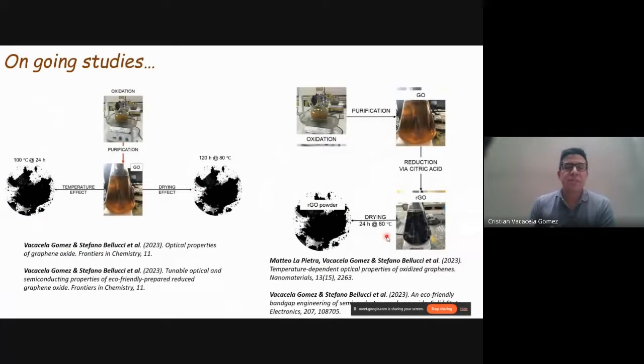Another important thing that we need to keep in mind is, if we are going to synthesize these materials, we also need to control several parameters during the process. For example, once we get the graphene oxide dispersion, like here, we can play with the temperature effect, for example, increasing the temperature from 40 centigrade to more than 100 centigrade to remove the water and just take graphene oxide. Or we can also increase the time.